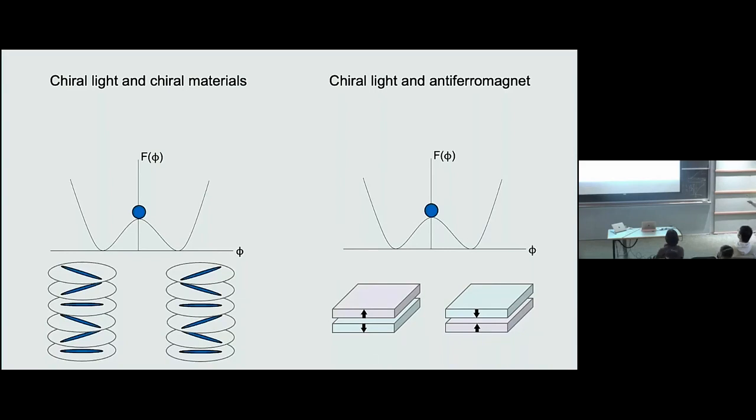I guess one similarity I see here is that chirality and this layered AFM state always come in two equivalent configurations, right? For chirality, it comes as left-handed or right-handed. For the layered AFM, it has this configuration and this configuration. And they are very symmetric in terms of band structure and everything. They are energetically equivalent. And you can imagine, without doing anything during material growth or phase formation, they must come in equal probability, right? There must be domains.